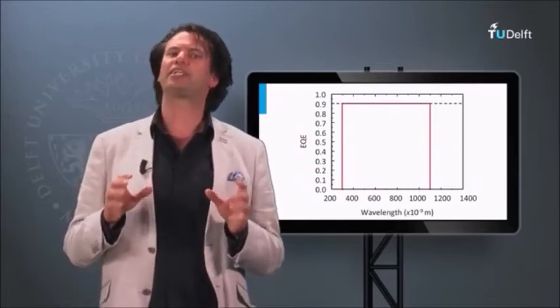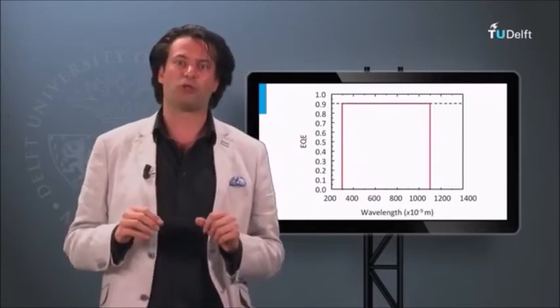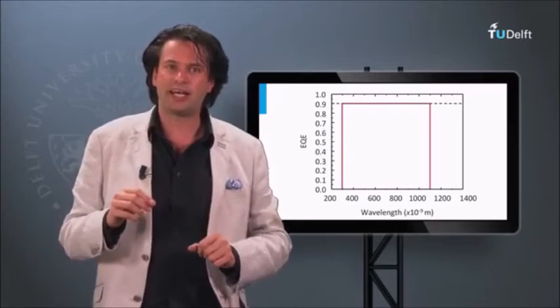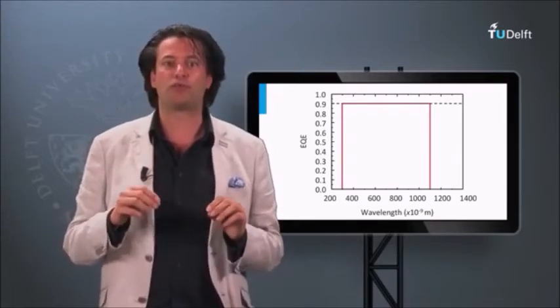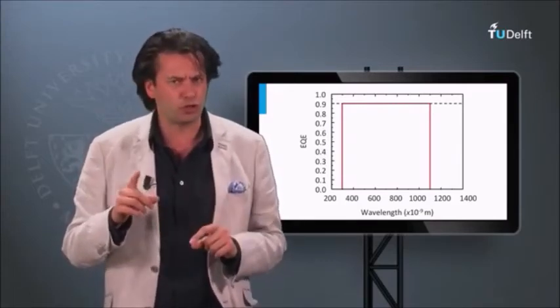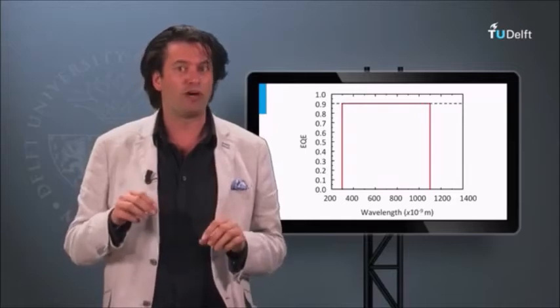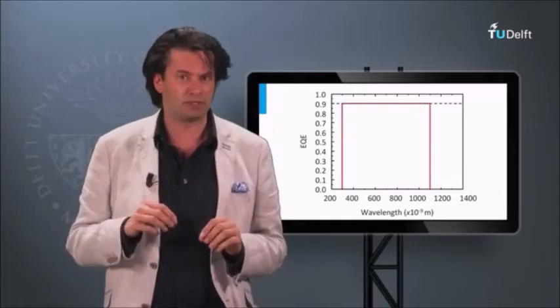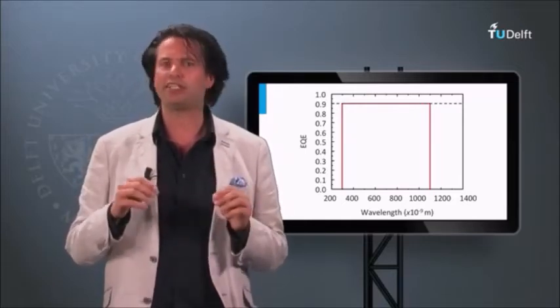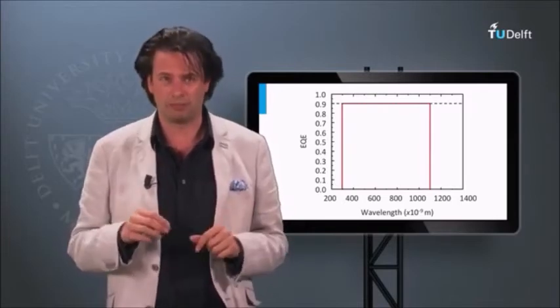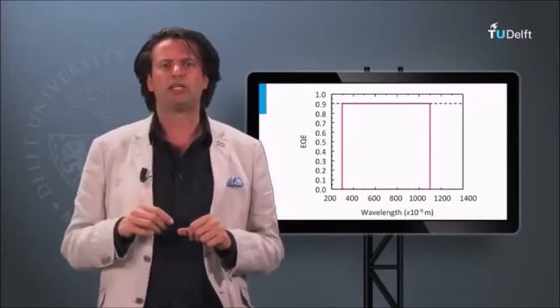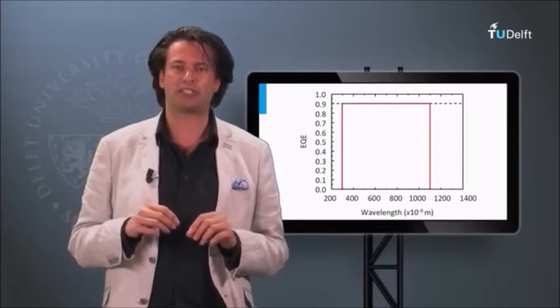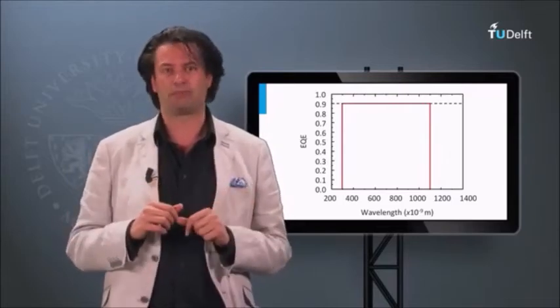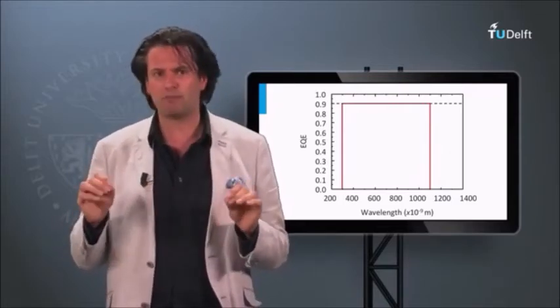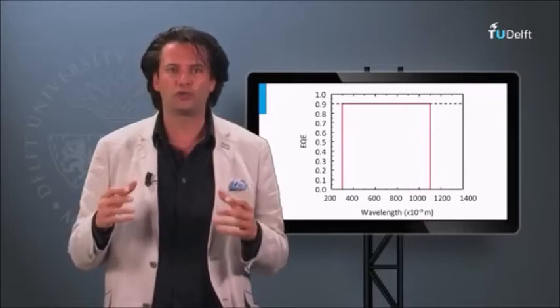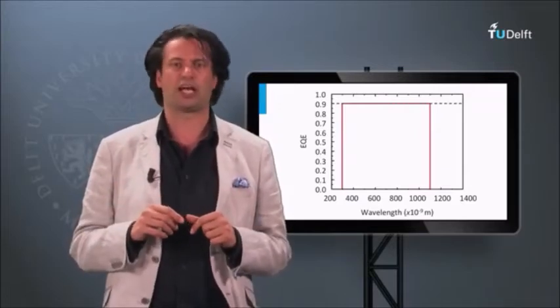Let's consider crystalline silicon as absorber layer. Crystalline silicon has a band gap of 1.12 electron volt, which corresponds to a wavelength of 1107 nanometers. For simplicity, we take 1100 nanometers. And we assume that the EQE is 90% above the band gap. Or in other words, 10% of the photons do not result in the collection of an electron.